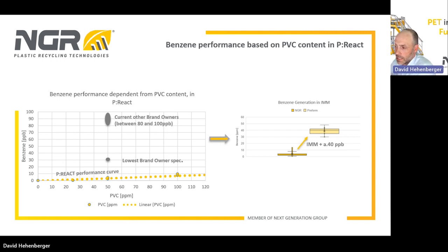And as you can see in the picture, we add here 25 ppm, we add 50 ppm, and we add 100 ppm of PVC into virgin material, and we found out with 50 ppm less than 10 parts per billion of benzene in the pellets. So this is really way lower than what the brand owner allows.